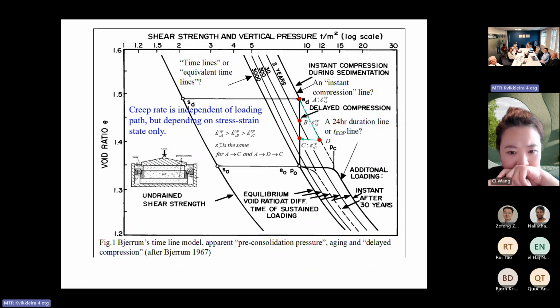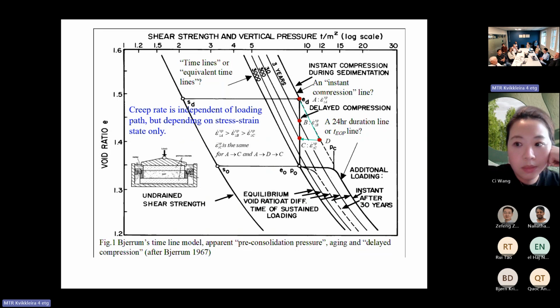But into this, and also into your models, we wanted to study this concept by laboratory tests. And of course, we have this creep, you're going downwards there, and we're talking about 300 years and 3,000 years. We cannot wait so long. So what we were doing was a creep test in a triaxial test, to also have control of the K-zero, because if you are in an odometer, you don't have control of the K-zero. So we were creeping for 1 year. And then we wanted to check whether we can find these isotache lines by unloading.